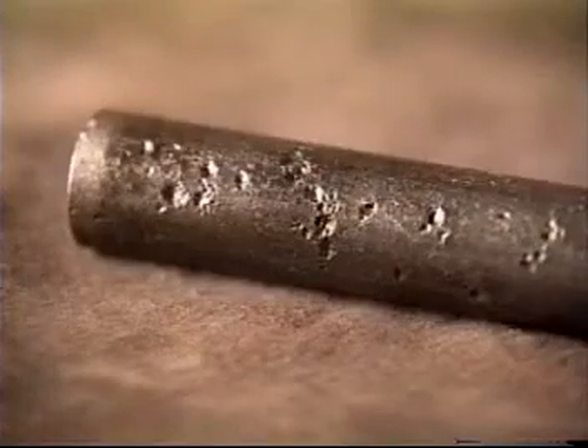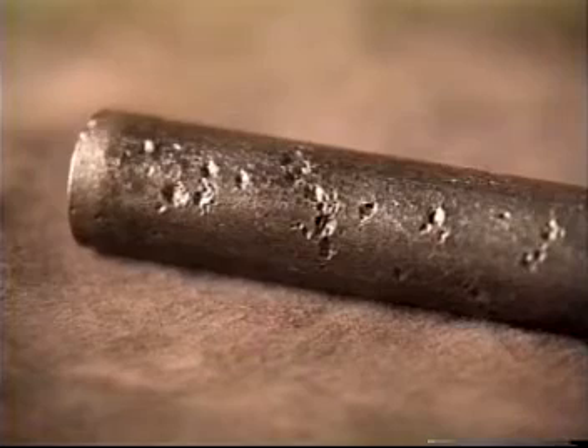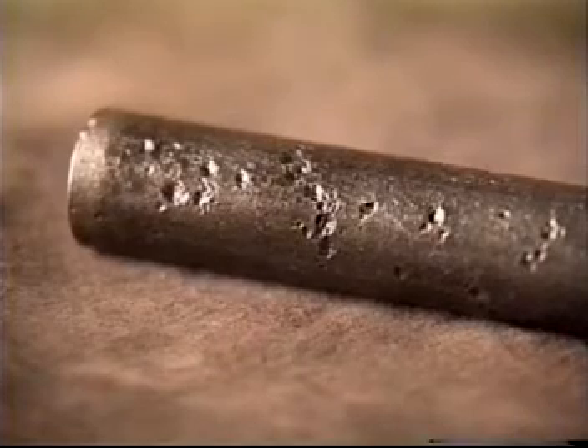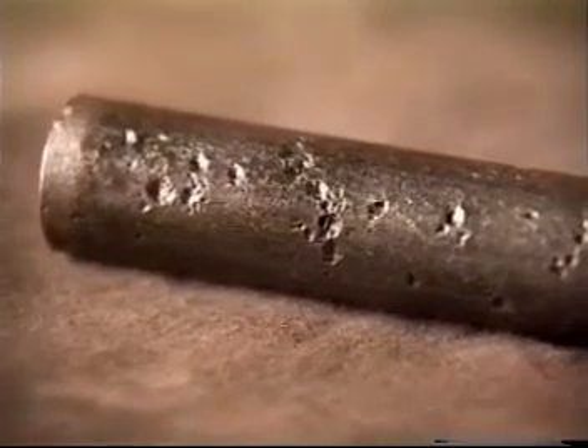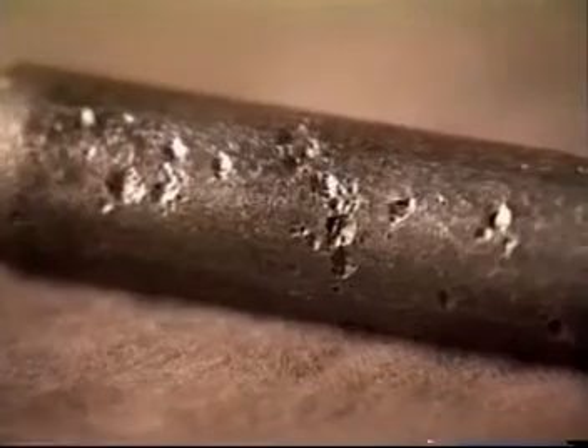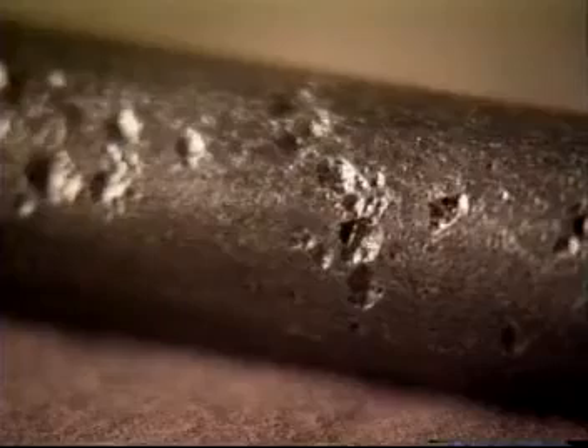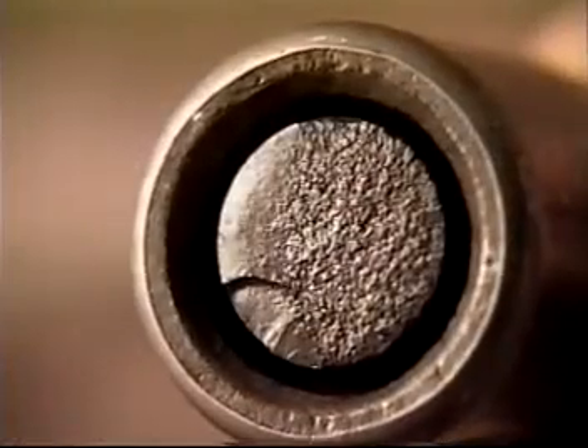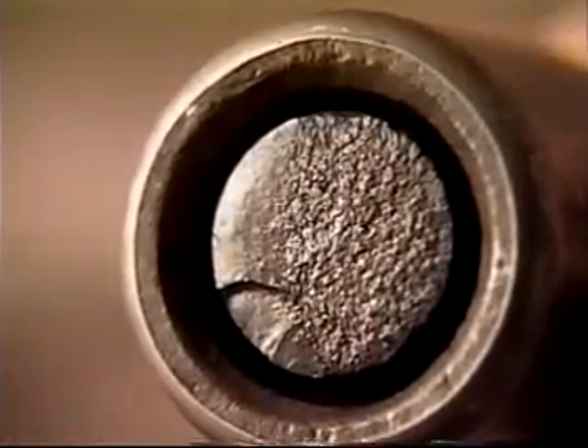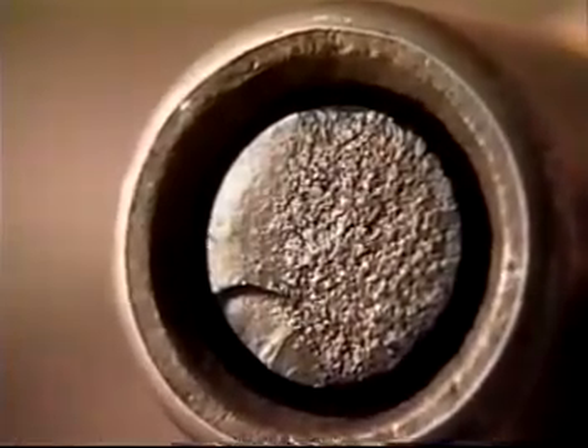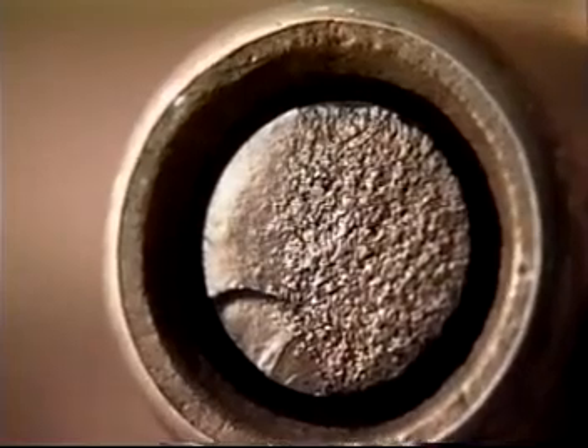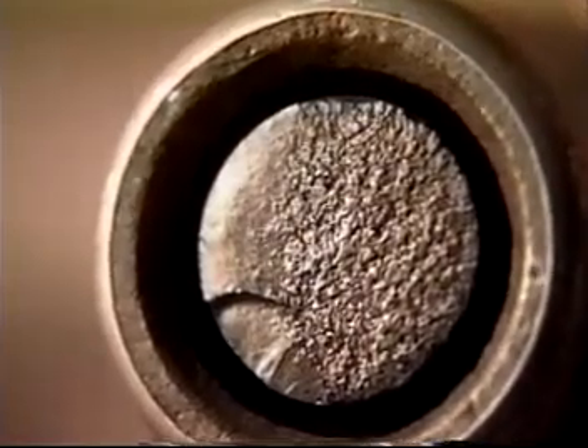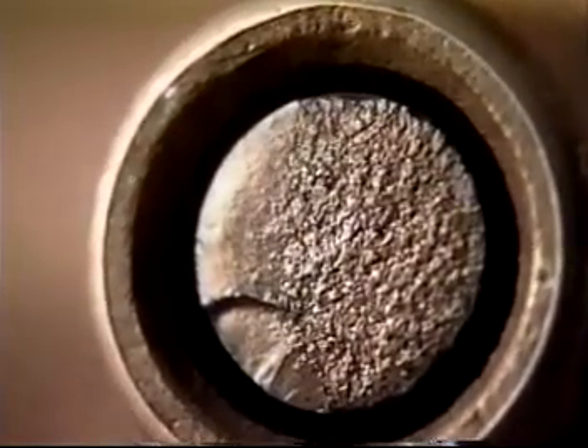H2S, or hydrogen sulfide, can also produce extreme damage to sucker rod strings. H2S attack results in pits that are random over the rod, deep with steep walls and round bases, with beveled edges and a stress crack in the base of the pit. H2S can also cause embrittlement, which will exhibit a granular break face. The initiation point may or may not be visible, and a fatigue area may not be present.